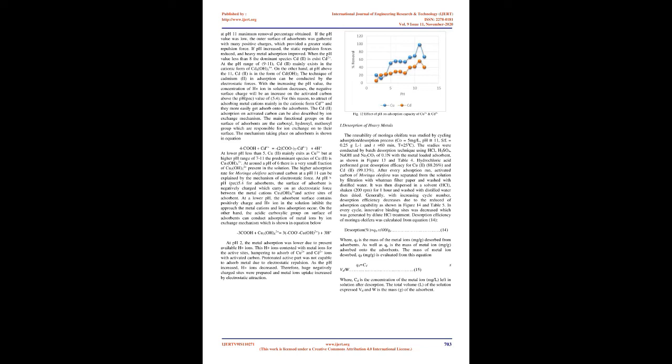Within 10 minutes, for all initial concentrations in mg/L, 100% of copper was removed and the adsorption quantity was 20.45 mg/g, but after 120 minutes at equilibrium, copper removal was slightly decreased to more than 98%, as shown in Table 3. In contrast, the removal percentage of cadmium was 100% for concentrations of 1 and 2 mg/L and more than 96% for 5 mg/L in just 10 minutes, but after equilibrium the removal of cadmium decreased to more than 56%.